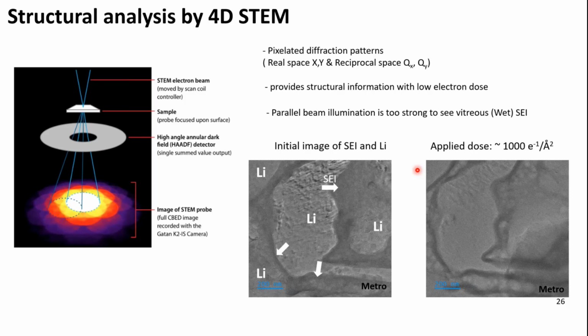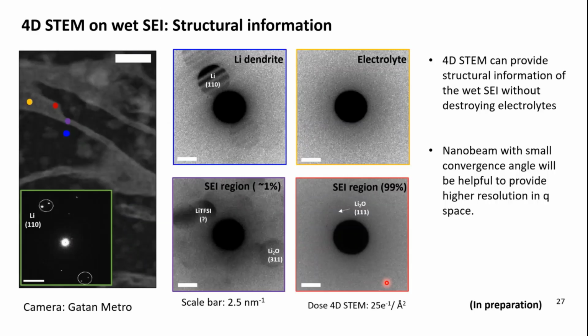So you can see there are no such spider web structures coming from the vitrified SEI. After I tried to look at high resolution images there, I totally damaged the vitrified electrolyte. So in this regard, I believe 4D STEM is a really important tool to get structure information. This was two weeks ago, so there is still plenty of room to increase resolution in Q space by using nanobeam.